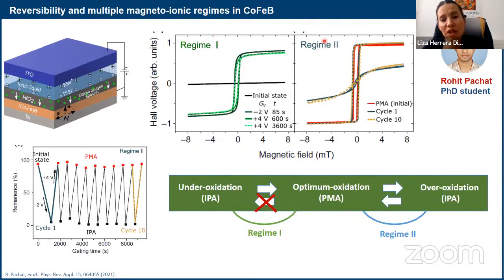But then we looked at regime 2, and regime 2 is perfectly reversible. So we can go very nicely from in-plane to out-of-plane magnetic anisotropy. We can cycle it. So here we realize that it's much more complex than just something related to that particular oxide. It's really the different types of chemical reactions that can happen, even in the same material, that can give you reversibility or irreversibility, in the same material with the same oxide and the same magnetic film.